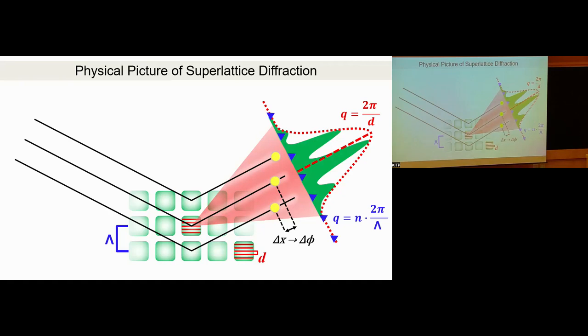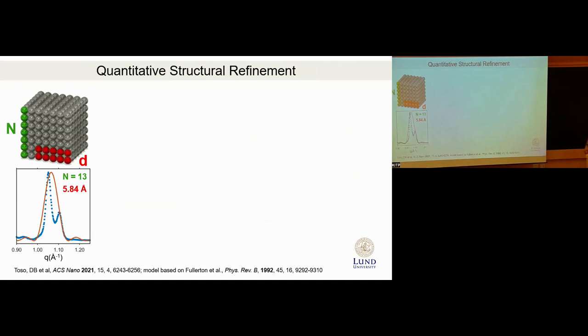Now, this has been known in epitaxial superlattices of III-V semiconductors and metal films. In the 80s, by metal sputtering, people were making all kinds of tungsten, copper multilayers for applications in high-density magnetic recording, and they observed this effect. They developed a numerical model that we adopted in order to quantitatively fit the experimental patterns. I won't show any equations because they're all in the studies, but I'll show the effects of each parameter.